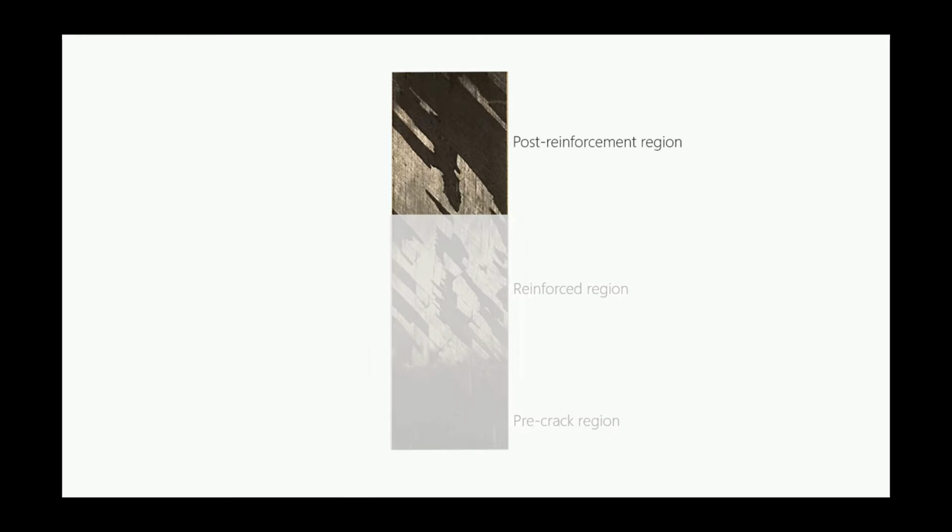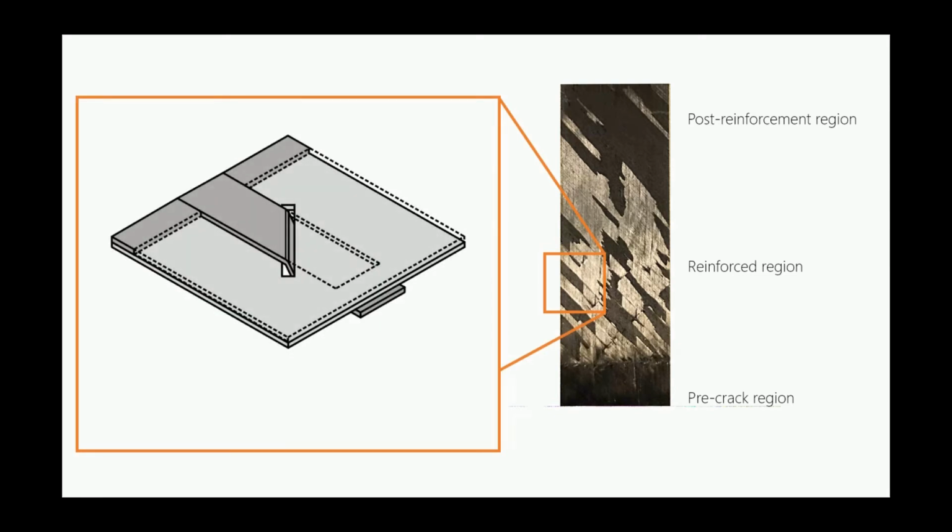From the fracture surface we can deduce the path taken by the delamination, which explains why the tabs did not affect the fracture toughness. Let's consider the crack path around a single tab and slit, shown schematically in the figure on the left. The tab starts in the top ply, where it is attached to the surrounding material. It then passes through the slit and ends at the indicated free end.